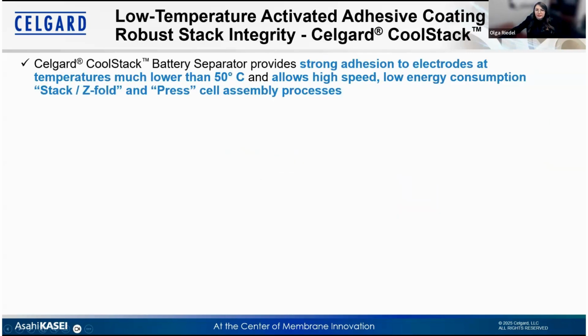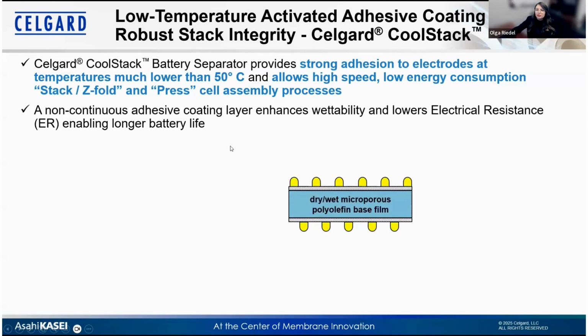Performance, however, is not the only challenge when it comes to large prismatic cells, as they are also commonly used in grid applications, but also the cell manufacturing itself. Nowadays, the majority of large prismatic cells actually use adhesive-coated separators to increase productivity and yields. Our newest adhesive coating technology, what we call CoolStack, allows for high-speed and low energy consumption stacking and heat press. But with the twist that we are actually not needing to heat press, but can also press the separator without applying any heat. So how does CoolStack enable such a good adhesion at low temperatures?